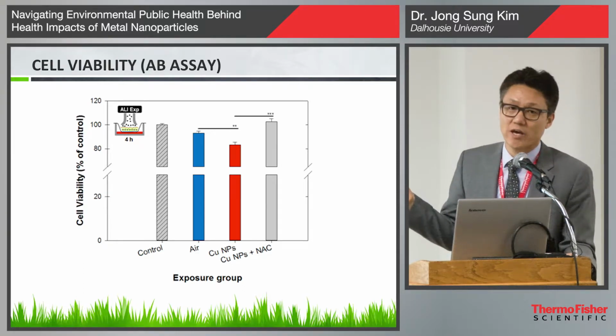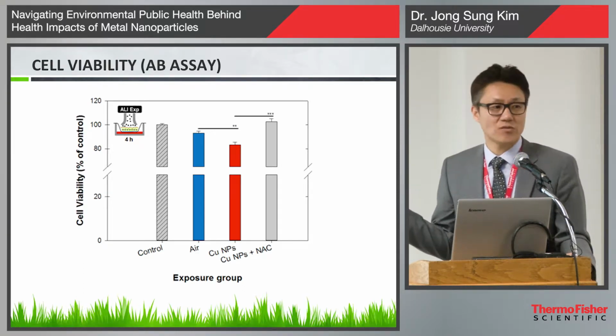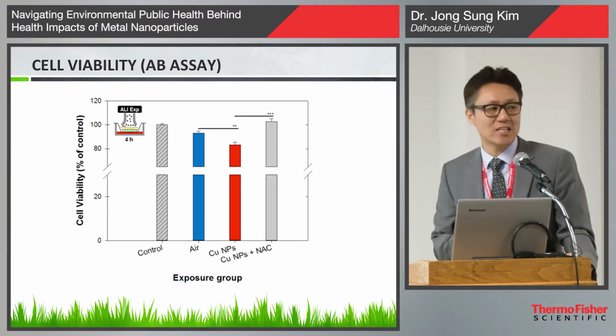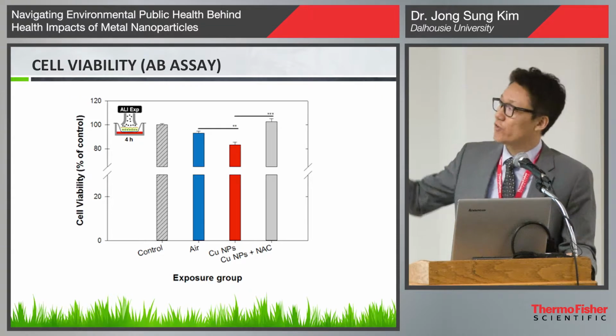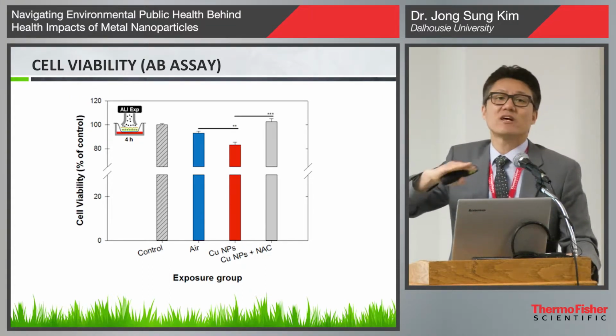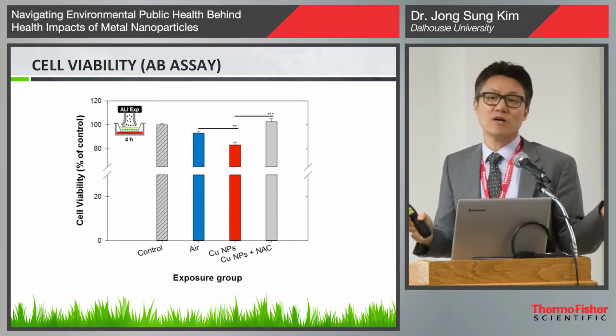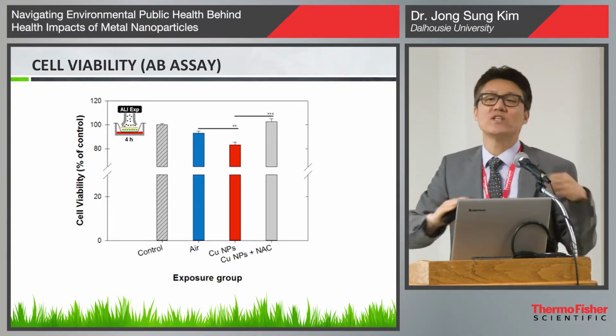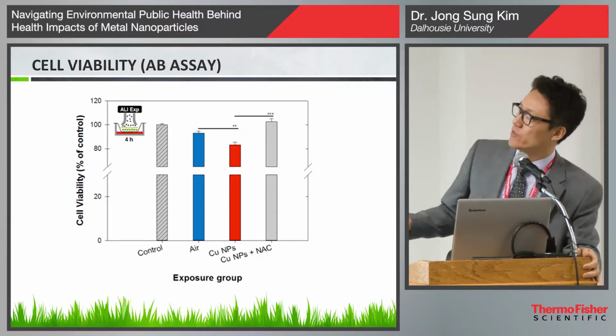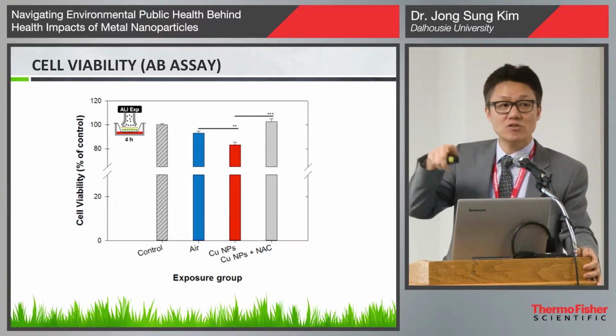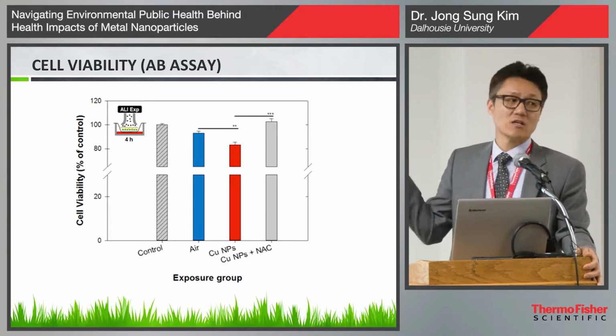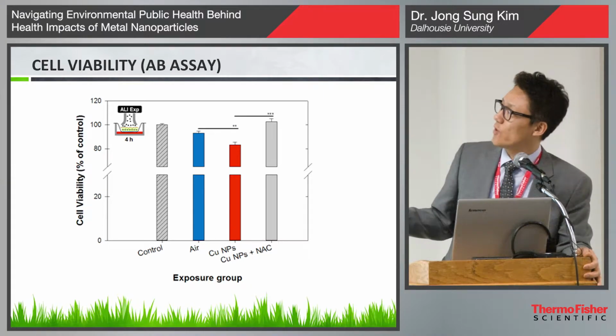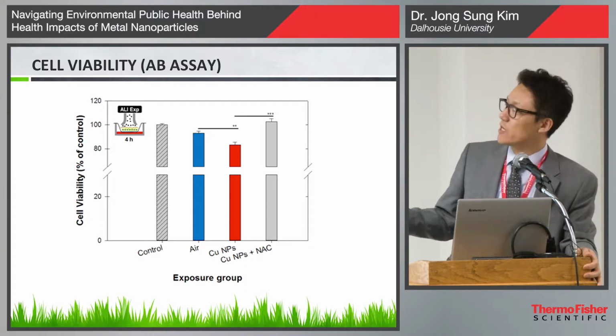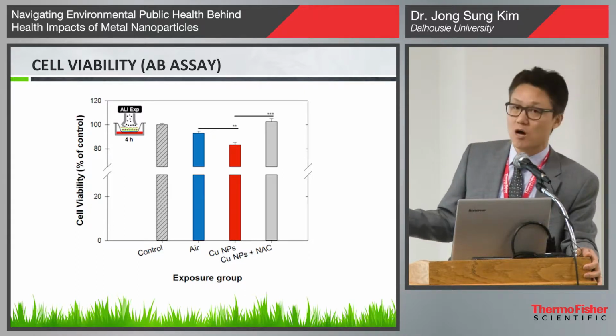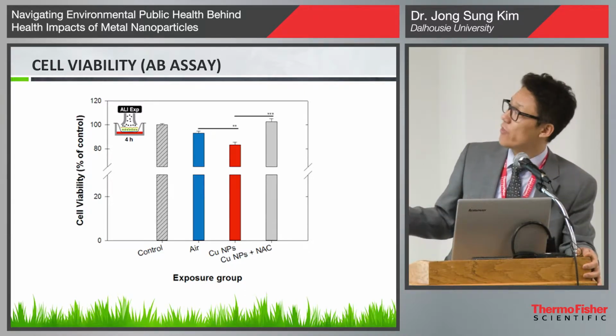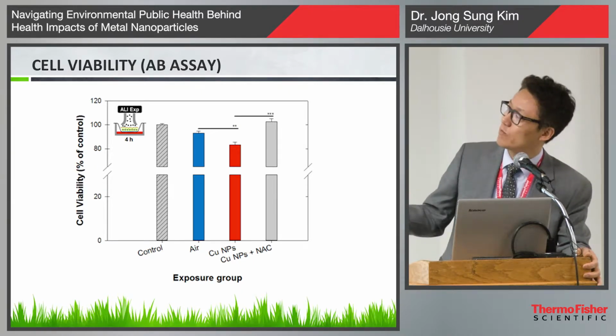So for cell viability we're using the Alamar Blue assay, which indicates the mitochondrial activity in the cells. Cell viability of 100% means the cells are completely healthy. So 10% cell viability means 90% of the cells are dying, only 10% of the cells survive. As you can see, the control and air. Since we are using air to deliver nanoparticle to lung cells, air is actually our control. So air didn't kill any cells significantly, and after our copper nanoparticle was delivered to lung cells, 20% of the cells are dying. So cell viability is 80%.